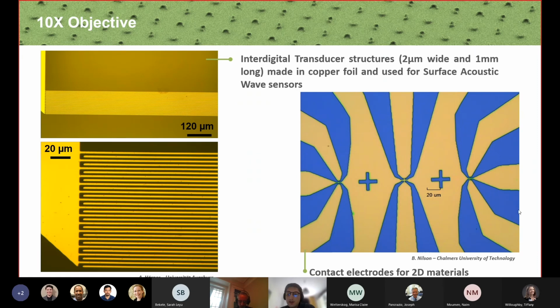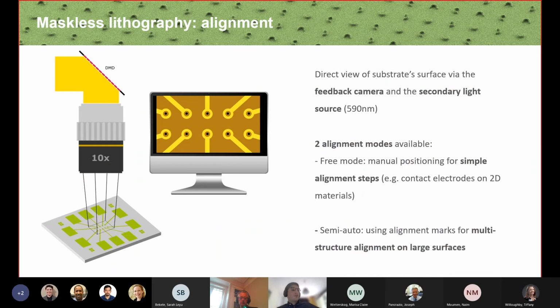And one more example here, it's also contact electrodes, typically for working with 2D materials. The idea here is to fabricate this contact electrode onto material that has been deposited here, and here. And the details here, sorry, I just missed the inset, but the details here are about 1.2, 1.3 micron. So you see that by pushing the limit of the machine, you can also go a bit under the resolution that we give, which is 1.5 micron. That was for some examples of fabricated structures.